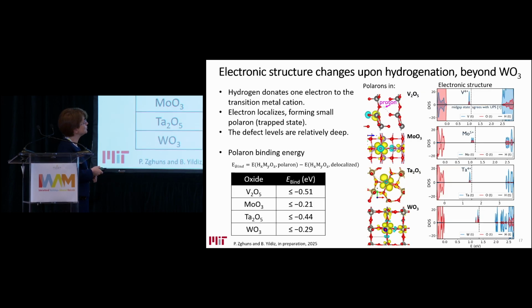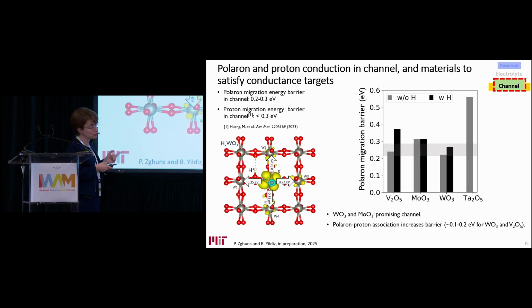And tungsten oxide is what we have most experimental experience with in this device, but there are other intercalation oxides that we are theoretically and experimentally assessing now. These include vanadium pentoxide, molybdenum oxide, tantalum pentoxide, in comparison to tungsten oxide, and all of them form polaronic carriers when you insert hydrogen into them. So polaron trapping or binding energy is negative in all of them, so we can leverage the same type of mechanism in these other intercalation oxides and not just tungsten oxide. But then you have to see whether these polarons are conducting enough, and there is a target migration energy for these polarons to give us the right conductance range to work with.